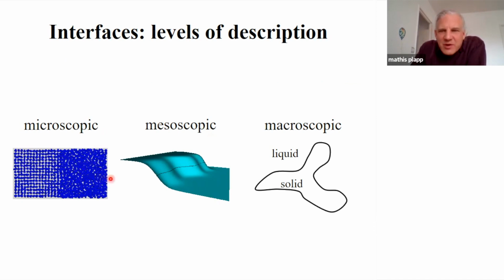So on the macroscopic scale, an interface often looks like a surface of discontinuity between two phases, between here solid and liquid. But obviously, if we look at it on the microscopic level, we know that matter consists of atoms. So the solid is an ordered structure and the liquid is a disordered structure. So we see that these can coexist. And in reality, in physical reality, the order doesn't stop suddenly, but it gradually decreases between the solid and the liquid, such that we have a transition zone, which is the interface. So to which we can thus attribute physical thickness.